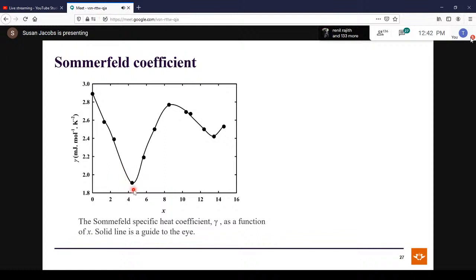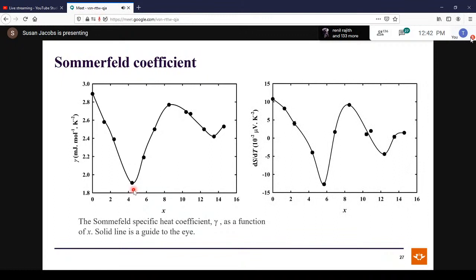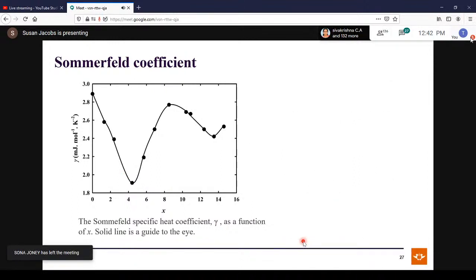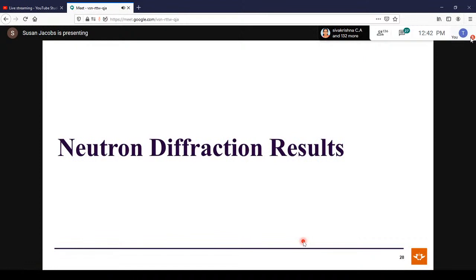And if you remember the Seebeck coefficient curve, it's very similar. The trends are very similar. You can see the deep minimum. So we decided we need to investigate this further to understand what is happening. And that's why we went to do neutron diffraction measurements.